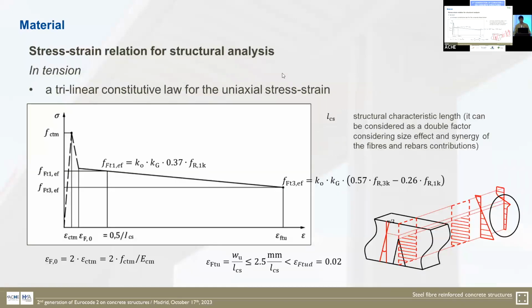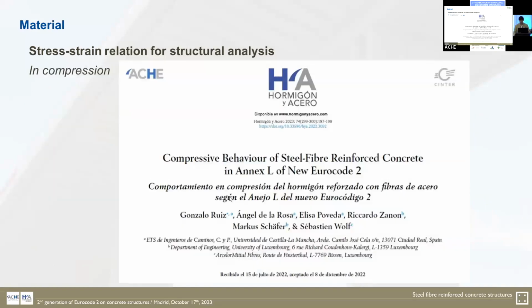So for nonlinear analysis, this is the suggested constitutive equation. It is a trilinear model, with the pre-crack constitutive relationship linear before the cracking, and then after the cracking we activate the post-cracking resistance of the steel fiber reinforced concrete, and we characterize this curve with these two values, the effective values of FT1 and FT3. For compression, I leave the floor to my colleague.